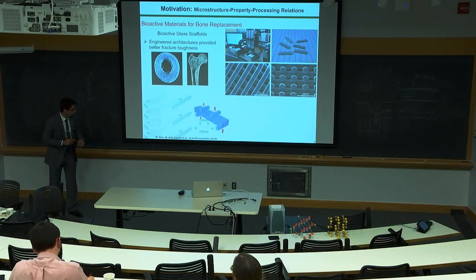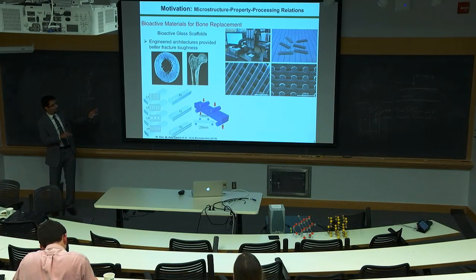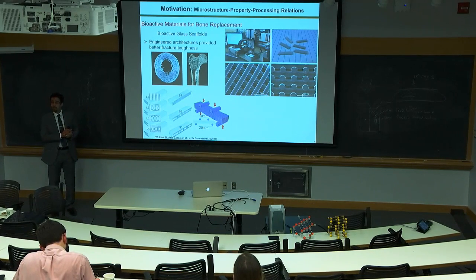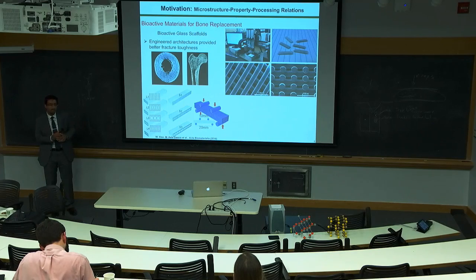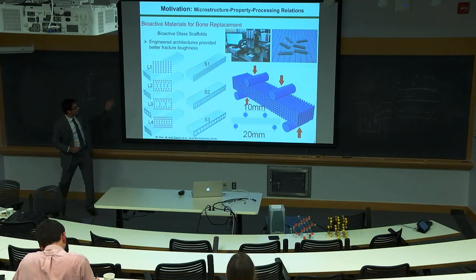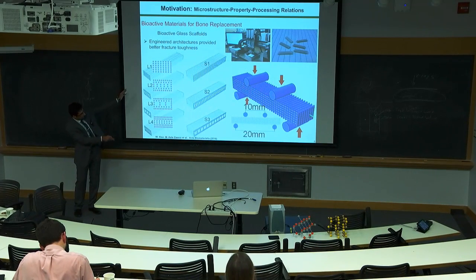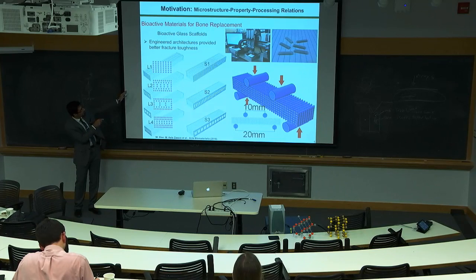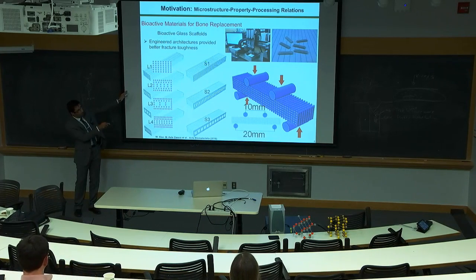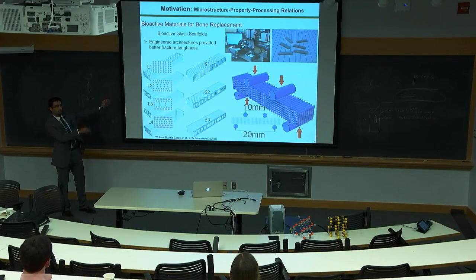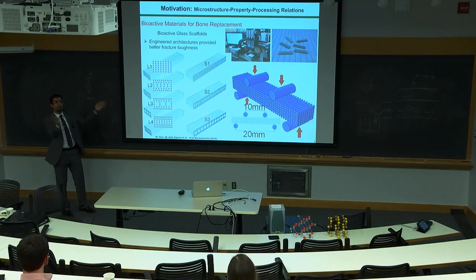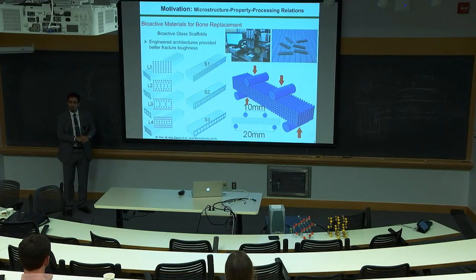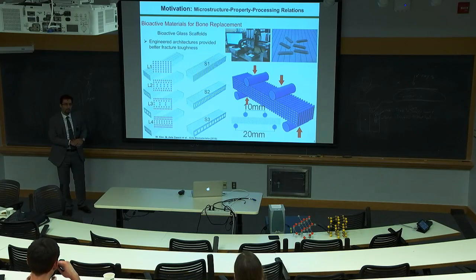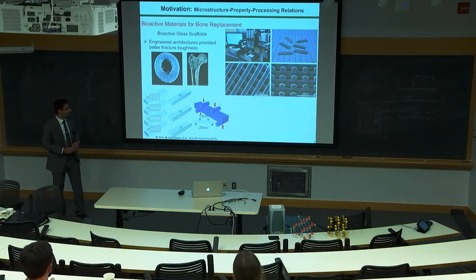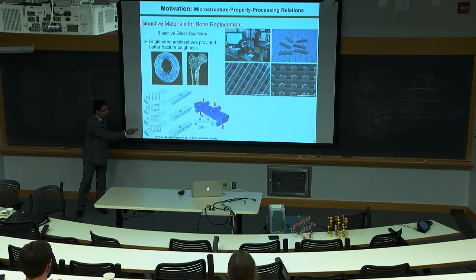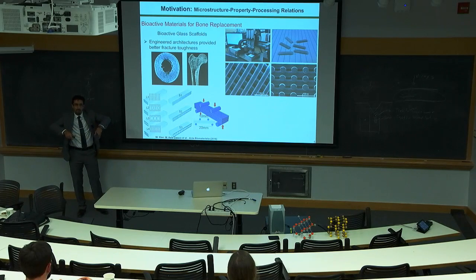So before doing trial and error in our lab, we did computer simulation. Let me make it a little bit bigger. This is what we have. This is the scaffold. We have long filaments designated by L, short filaments by S. So we can have different architectures, right? Let's mix them, run like 200 simulations, and see which one will give us the best flexural strength. And we did that. This is the assembly of 4-point bending. So we are bending the scaffold.